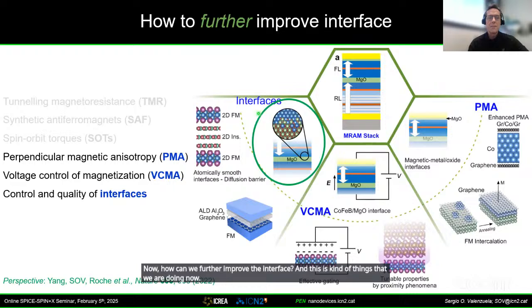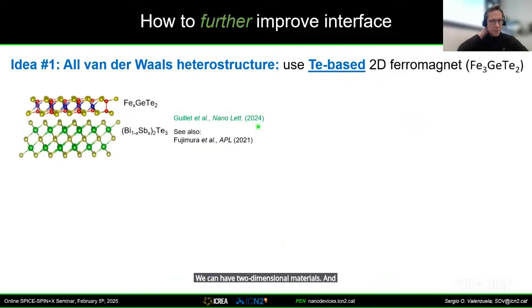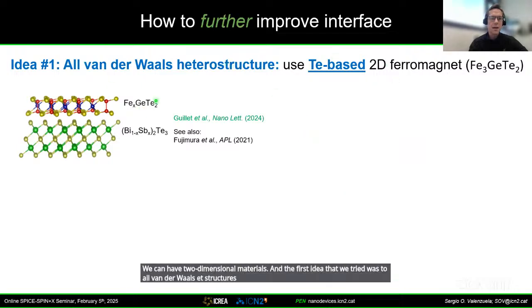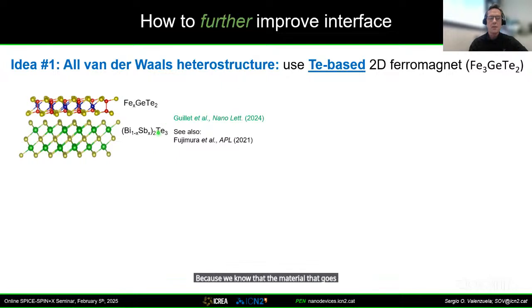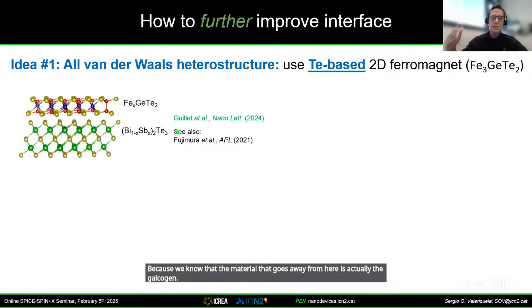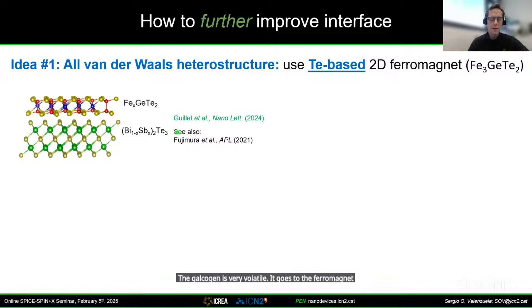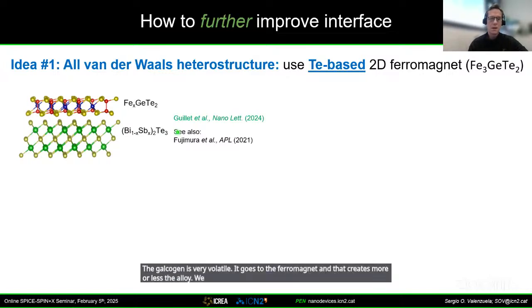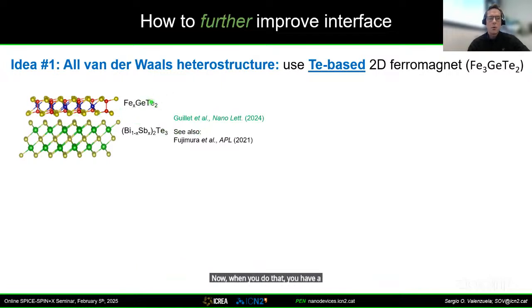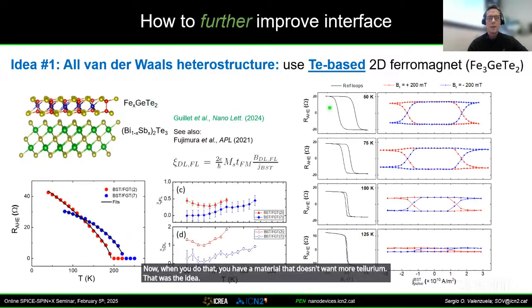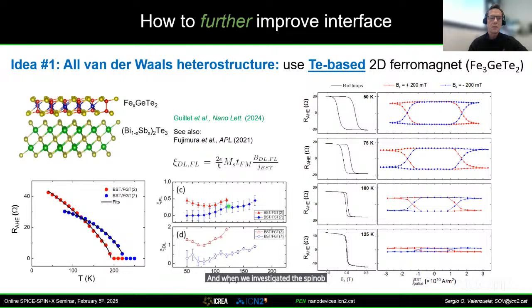We can have two-dimensional materials. And the first idea that we tried was to look at all van der Waals heterostructures, and we chose a ferromagnet that has tellurium in it, because we know that the material that goes away from here is actually the chalcogen. The chalcogen is very volatile. It goes to the ferromagnet, and that creates more or less the alloy. We see this by XPS methods. Now, when you do that, you have a material that doesn't want more tellurium. That was the idea. And when we investigated the spin-orbit torques in this situation, we get much larger efficiency and also switching current that are very decent for these systems.